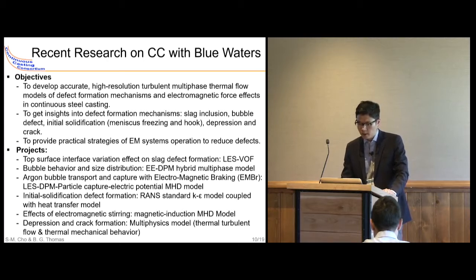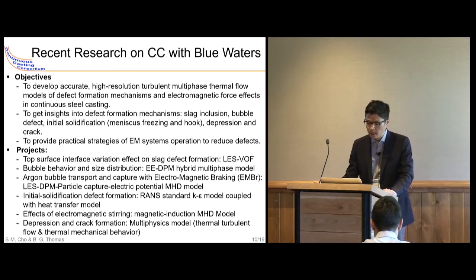And we also investigate the effect of electromagnetic stirring on the initial solidification defect using the magnetic induction MHD model. And finally, we simulate the depression and crack formation using multiphysics modeling, which couples the thermal turbulent model with the thermal mechanical behavior model.